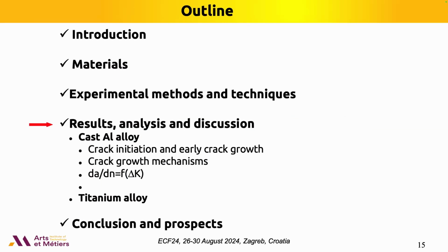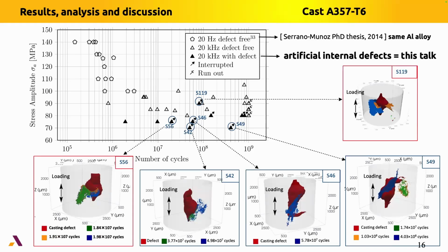So now I'm presenting the results and the analysis and the discussion of our results. First, I'm presenting the results about crack initiation, and then we will see the crack growth mechanisms and the Paris diagram. So first, I'm presenting the results in a classic Wöhler diagram. Our results are the symbols in black, and the open symbols correspond to literature data on the same alloy published by Serrano-Munoz. You can see that the results we obtain are in agreement with the results of literature, especially because in a very high cycle fatigue regime, the results have a large scatter.